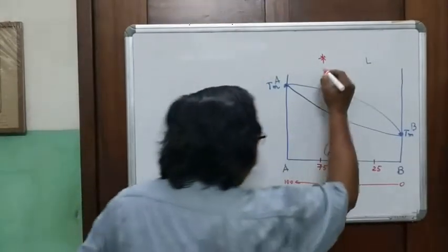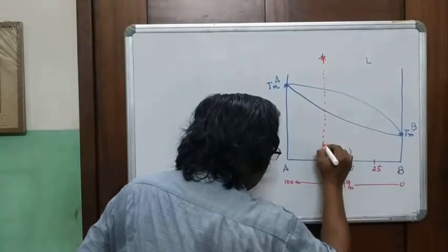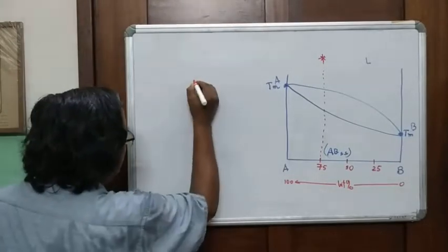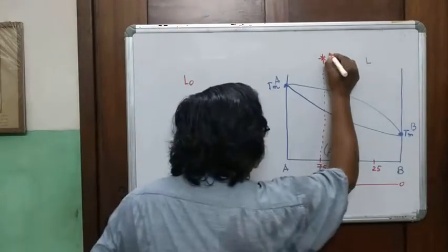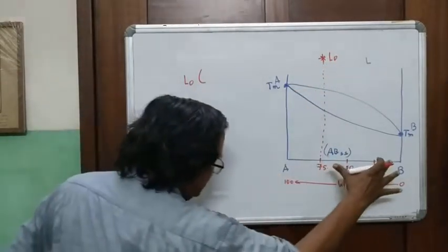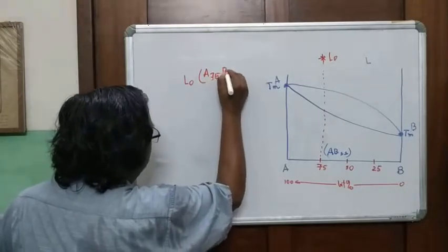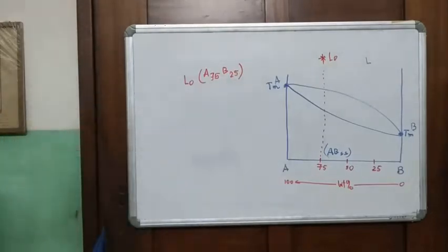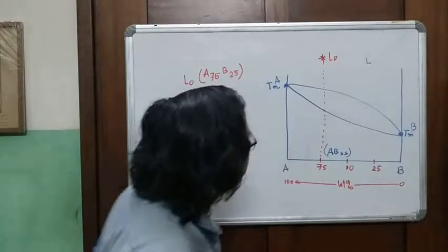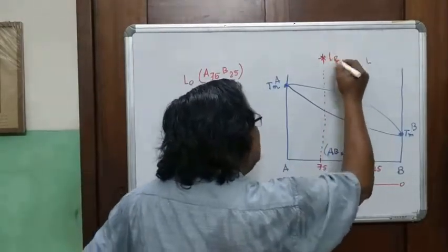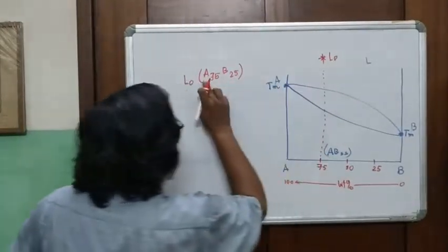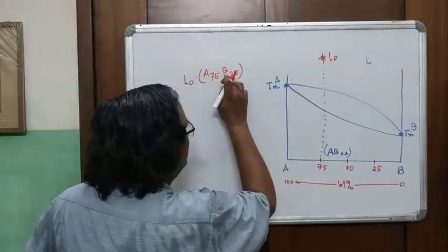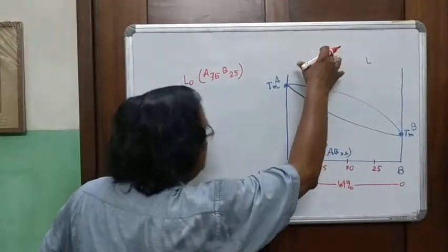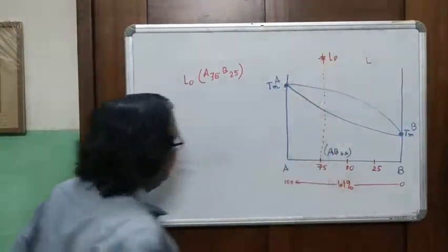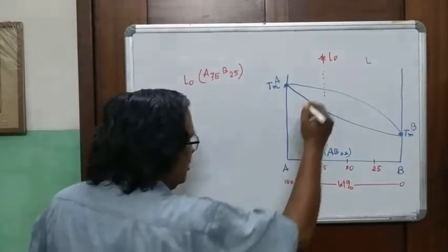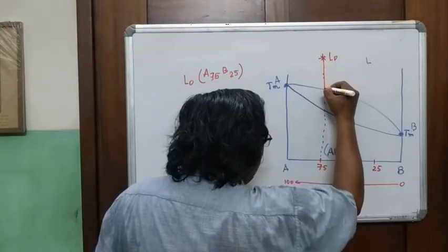So now, if we take a melt at this composition, the composition of the melt at this point of time is the initial composition, and we write this as L0, and with L0 the composition is A75 and B25. This is the composition of the initial melt. Now, if we cool down L0, A and B components of the melt are present in the ratio 75 A and 25 B. And if you start cooling it, obviously the temperature goes down along this isopleth and reaches this point.